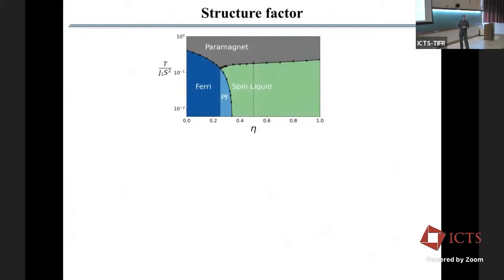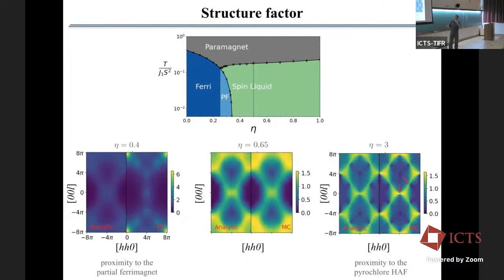Now, what if we want to characterize this phase? The best way, I mean, we are used to it. Spin liquid, we don't have broken symmetry, we don't have other order parameters, so we use the structure factor. And these are the structure factors as would be seen by neutrons, so they are without the parallel component to the Q vector. So this structure factor, when eta equals 0.4, so here in this region you have Bragg peaks. That's long-range order. Ferrimagnet or partial ferrimagnet, you have Bragg peaks. Then when you are just next to this, in this region here, you see these diffuse scatterings.